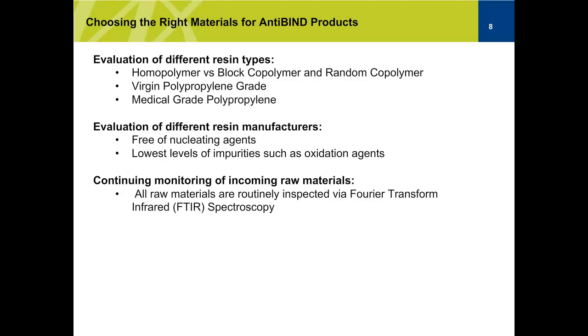Polypropylene resins, or the raw stock, can come as a homopolymer, block copolymer, or random copolymer. Of course, we went with the homopolymer because it has the lowest amount of extractables and better clarity than the others. We made sure we use the virgin polypropylene grade, which means we did not use recycled polypropylene, and then we also used medical grade polypropylene, which means it's low in extractables and leachables. Now, even though you can find a lot of companies offering these kinds of resins, what we have found is the amount of impurities in the polypropylene resins or raw materials also varies from one company to the next. So we have evaluated different resin manufacturers, and we were able to choose one that gives us the least amount of impurities and one that is free of most extractables and leachables.